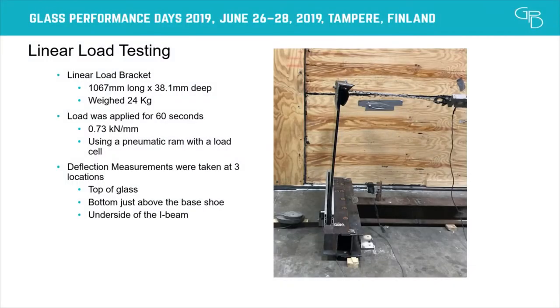So for the linear load testing, we had a bracket made that went on top of the glass, and you could see it up here. It was the length of the glass, and it was only about 38 millimeters down from the glass, so it was a pretty thin load, a line, and it was pretty heavy, it weighed 24 kilograms. The load was applied for 60 seconds, and it was done with a pneumatic ram.